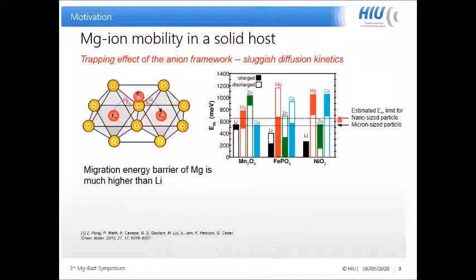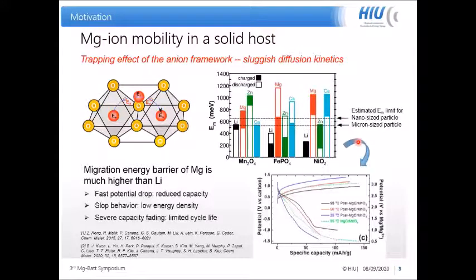So with this theoretical prediction, I would say it's not surprising that in practical cases we normally see this sloping behavior with a fast potential drop in the voltage profile. As this figure shown by Brian before, we see that even at elevated temperature, the magnesium storage in spinel oxide is still very limited. And this usually leads to a very small capacity with limited cycle life.